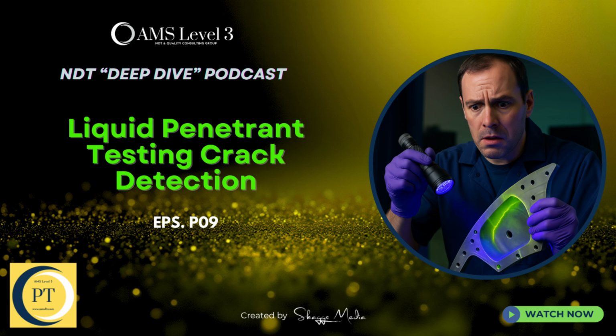But, and this is critical, you have to control the emulsifier dwell time very carefully. Leave it on too long, and it can actually start to diffuse down into the flaw and emulsify the penetrant you wanted to keep. Oh, so it can undermine the test from the inside out. It can completely remove your indication before you even get to see it. So yeah, mastering that removal step, whichever method you use, that's really a key part of the art of liquid penetrant testing. We'll take a quick break, and when we come back, we'll talk about the developer, how we finally make that hidden flaw visible.